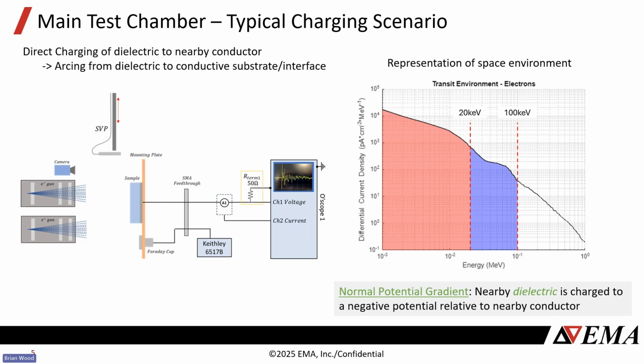While that's charging, we do have the capability, like I mentioned earlier, to sweep the surface voltage probe across the sample. We are simultaneously measuring the flux with the Faraday cup. I didn't mention it earlier, but we do have a camera pointing at the sample, and with some capture software, we're able to capture any arcing behavior that is visible. We can capture those really well, and that's the cool part of these projects, being able to capture the visual signature of the arcing behavior.